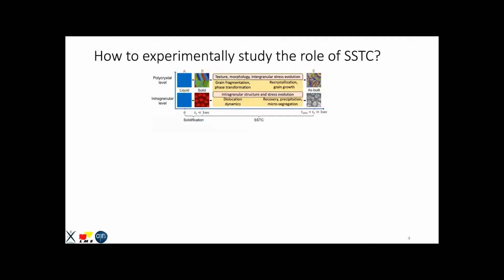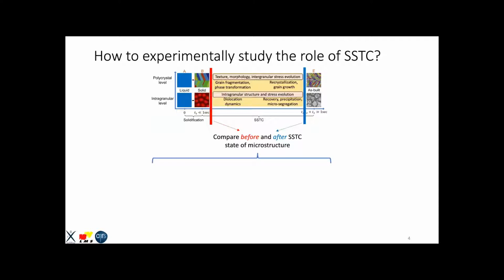Okay, so from an experimental standpoint, how can we study the role of solid state thermal cycling? Well, it's rather simple. You just compare the microstructure before and after solid state thermal cycling. Of course, it's easier said than done. There are two ways to go about it. The first one is operando techniques, which we saw earlier this week, where you have sufficiently time-resolved equipment that you can use to measure the microstructure changes continuously as your additive manufacturing process proceeds. For example, using synchrotron XRD that Stephen showed, or radiography that Philip Withers showed.